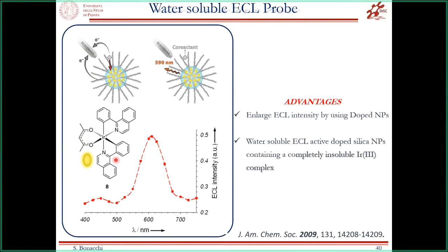Instead, in this case, we can trap a high number of iridium complexes inside this water soluble and highly stable structure, and so we are able to not only optimize the ECL signal, but also to have an ECL probe that is stable for a long time in water.